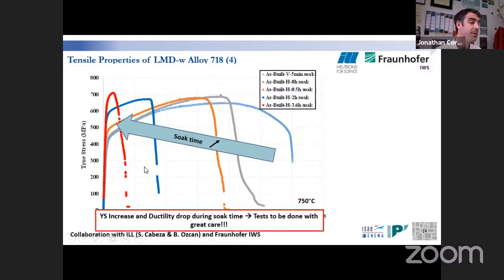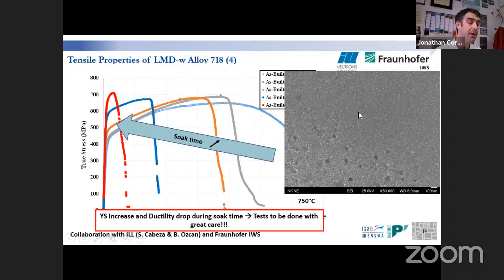And the increase in yield stress is directly coming from, and that's a picture I took last week, is directly coming from the in situ precipitation during the soak time before starting the test. While the decrease in ductility, we suspect to have environmental embrittlement of grain boundary. So it means that we need to take great care on the testing procedure if we want to characterize the properties of this class of alloy, which is unstable in this temperature range.